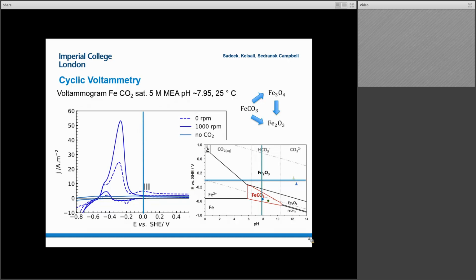And so what you can actually see is that in the case with no rotation, there's an additional set of reactions happening. And what's interesting at this point is that it's probably a combination of reactions. But moreover, it's probably a conversion of the iron carbonate either to magnetite or hematite directly, and potentially some interconversion. And I'm going to get to that in a minute. But it probably has a multitude of forward-based reactions.